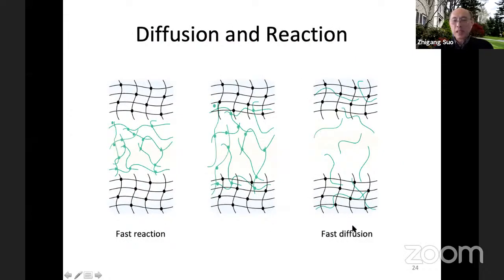Reaction and diffusion both need to happen, but neither can be too fast. For example, if your reaction is too fast, before the polymer chains diffuse into your network, you already reacted into a network, then you just have two networks without connection. Bad, low adhesion. Or if diffusion is very fast, the polymer chains already diffuse into the gel, and you don't have a network forming here. Again, there's no adhesion. And there's, of course, a happy middle ground you need to find.